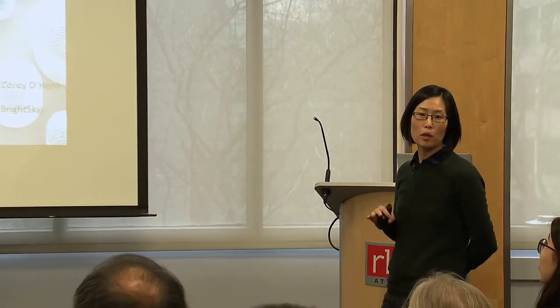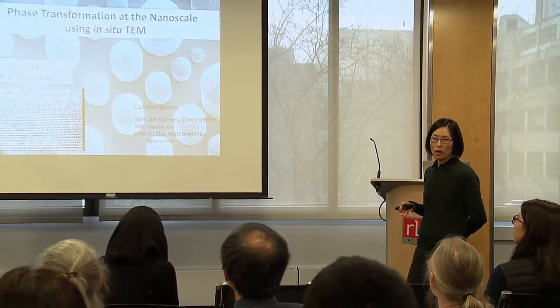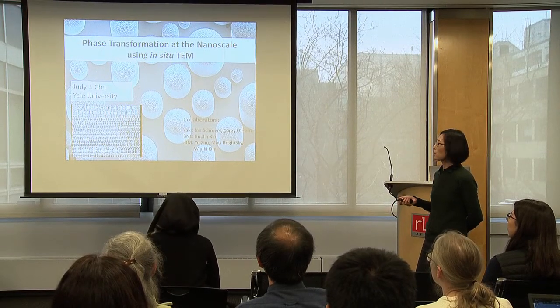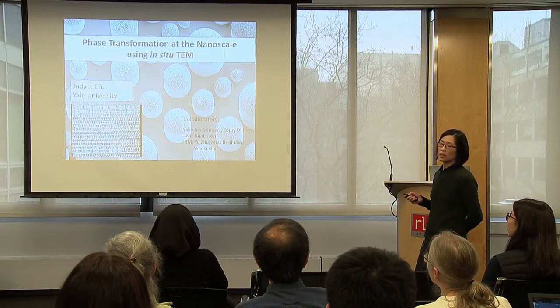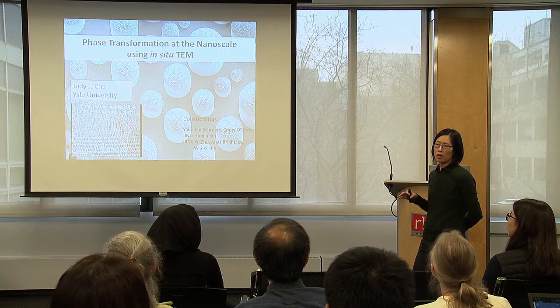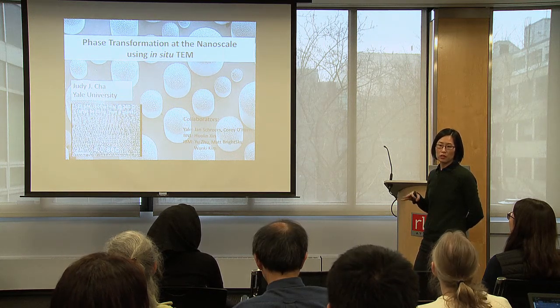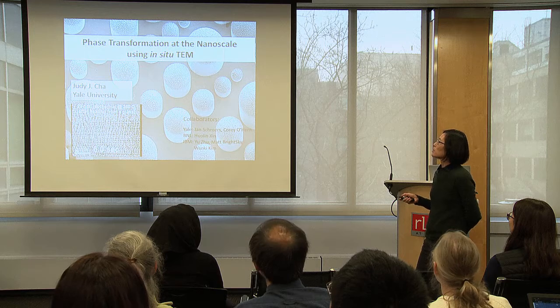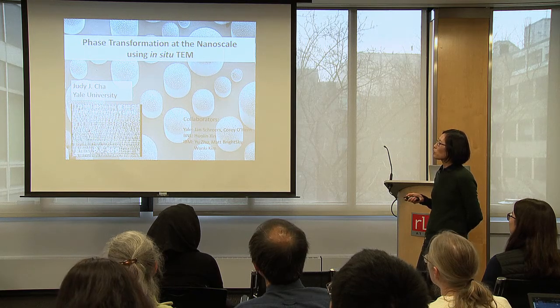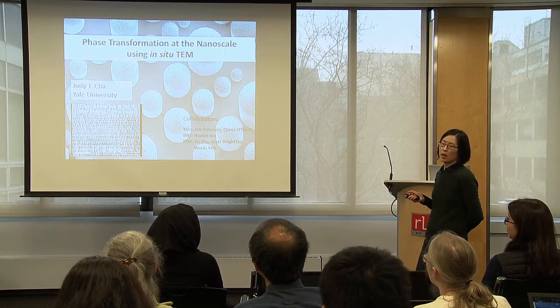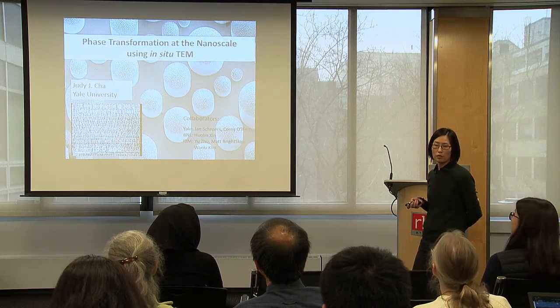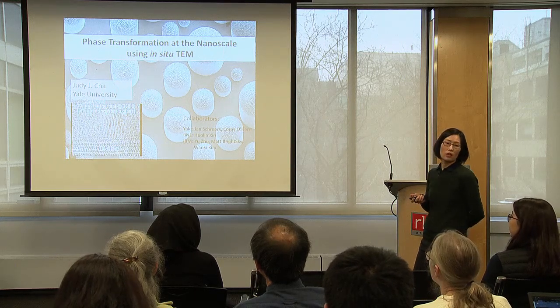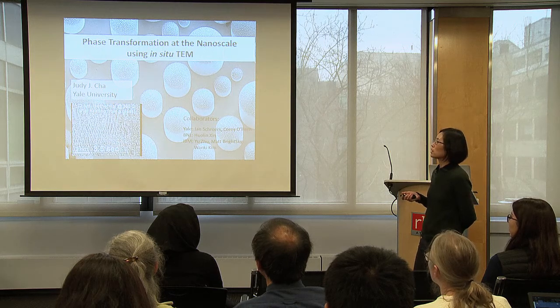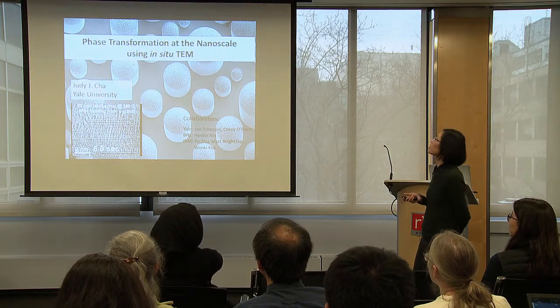This is sort of the latest experiment that we did. This is metallic glass, an amorphous metal in nanorods, so that we can directly image them inside the microscope. We did this experiment in Brookhaven, using the aberration-corrected machine there, because Yale does not have an aberration-corrected machine. It's about 23 nanometers, and we're imaging atomic plane by plane growth of metallic glass nanorods. There's a lot that we can learn by doing this type of experiment. This is a heating experiment.